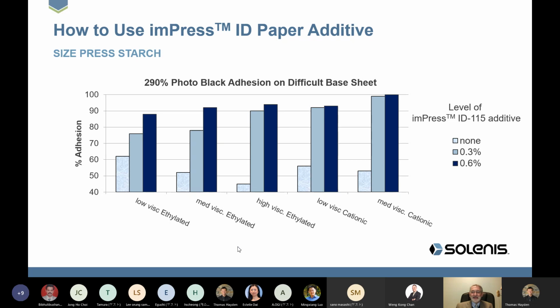And you can see as we put in 0.3% of our product, all of the materials did fairly well. In some cases, they didn't pass the adhesion target. Other cases, they did, and at the higher level, they passed easily. But what we saw, though, is we changed the starch, going from a low viscosity to a medium viscosity starch. The adhesion improved. Went to a higher viscosity starch, it became even better. And if we switched to a cationic starch, we got excellent results. And the higher viscosity cationic starches gave tremendous results, even on the most difficult situation.